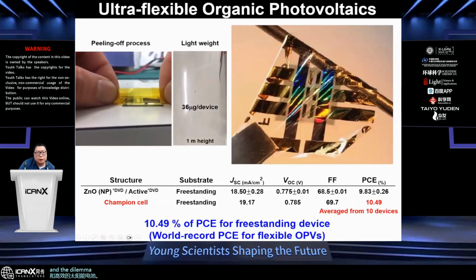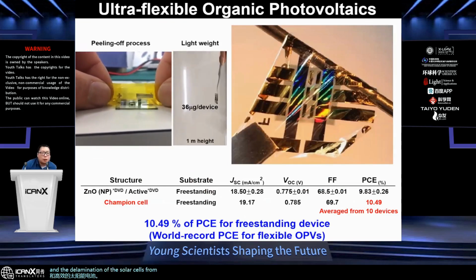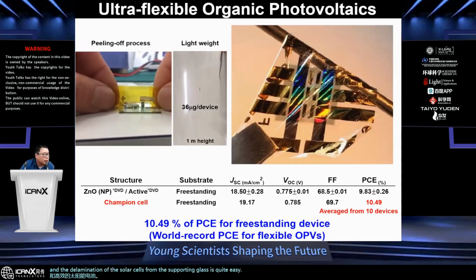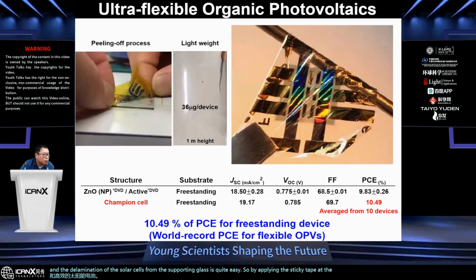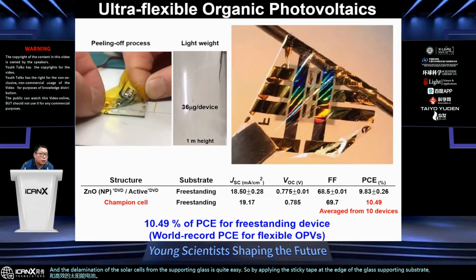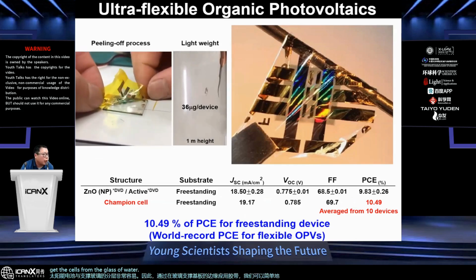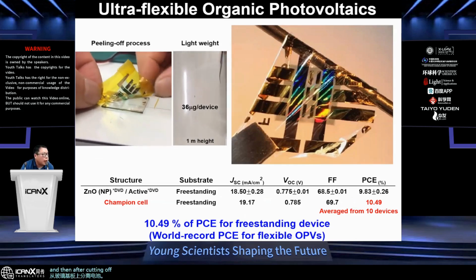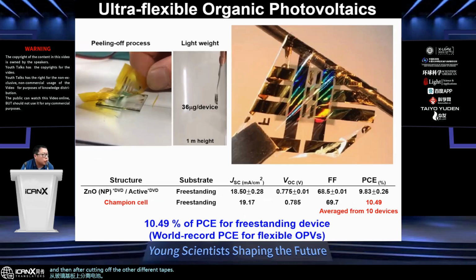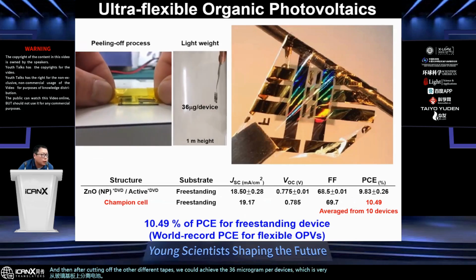And delamination of the solar cells from the supporting glass is quite easy. By applying sticky tape at the edge of the glass supporting substrate, we can simply detach the cells from the glass substrate. And then after cutting off the other different tapes, we could achieve 36 micrograms per device, which is very lightweight.